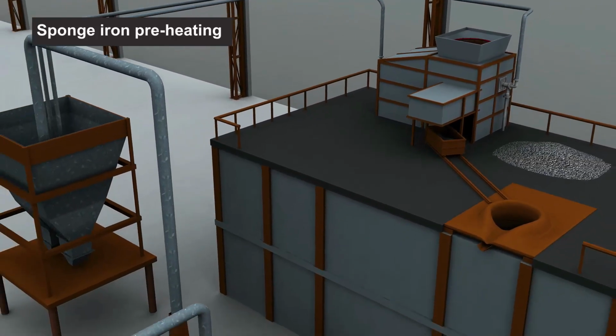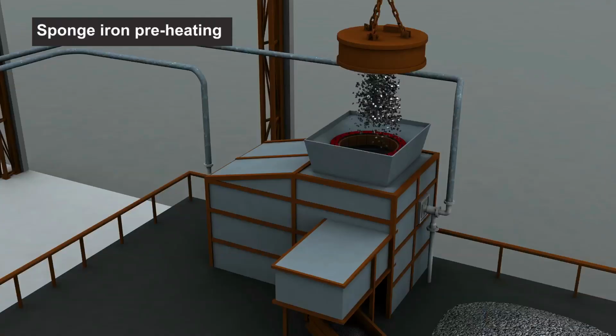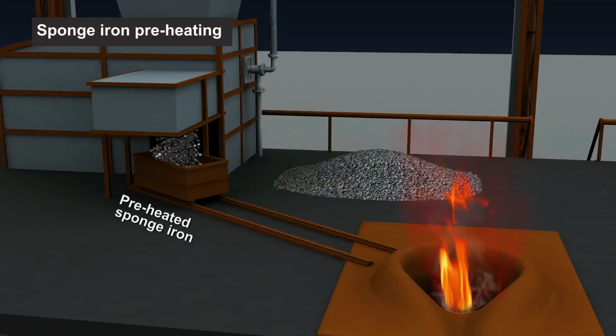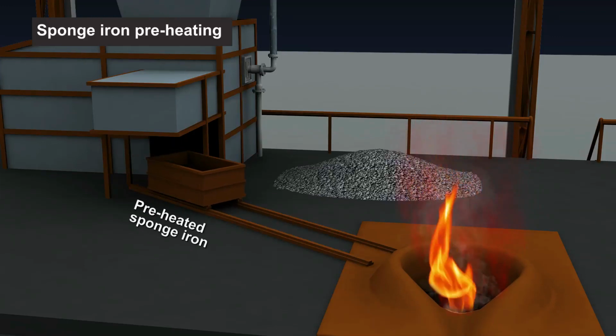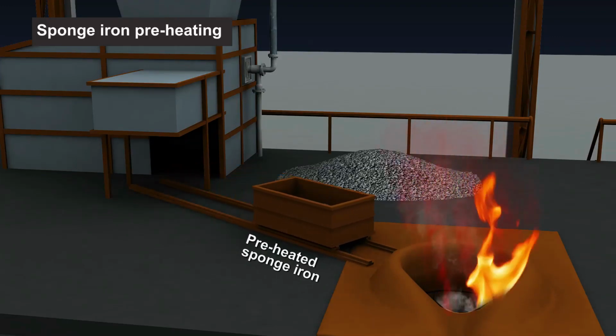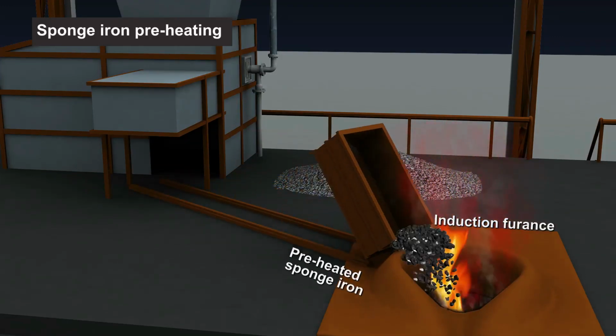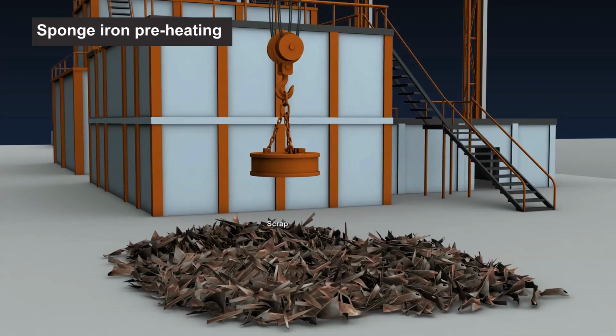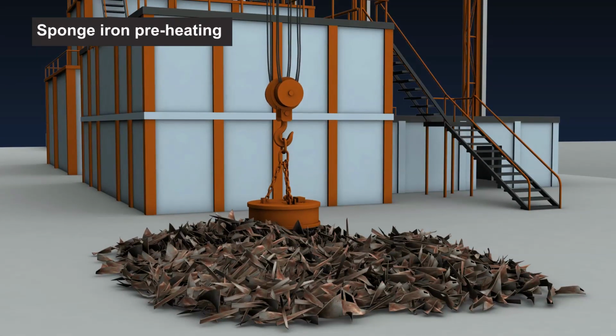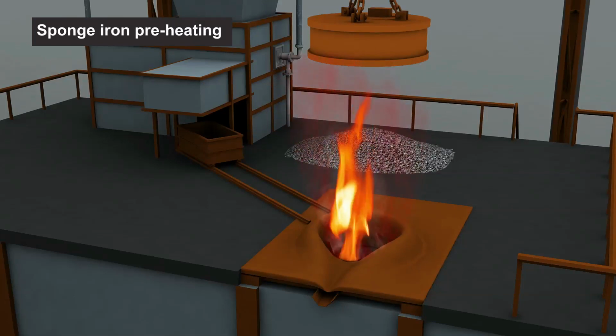Pulverized coal is fed into the kiln for combustion. After preparation, the preheated sponge iron is discharged into the collecting area. Immediately, a bucket conveyor carries the preheated sponge and feeds it into the induction furnace. The balance scrap required to fill the crucible is directly fed into the furnace at ambient temperature.